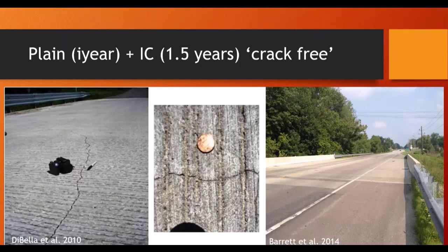When these were put in place, this is the conventional mixture. You can tell that it's got a very nice crack pointed out by that Sharpie pen that's there. So if that gives you some size scale, it is a very nice crack. Where the one on the far side is that third mixture that we talked about that was crack-free. Which one of these do we want?